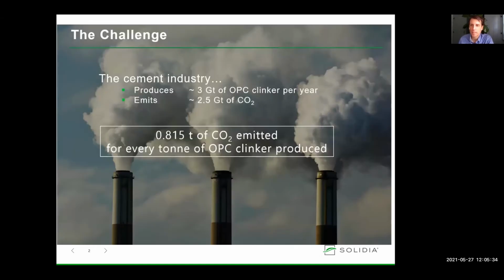I'd like to start off by stating a major challenge that we, the cement industry, are faced with. Annual global production of roughly 3 gigatons of clinker emits about 2.5 gigatons of CO2. On a per-ton basis, that's 0.815 tons of CO2 emitted for every ton of clinker produced. Solidia has precast and ready-mix technology solutions that can significantly reduce these emissions while simultaneously providing additional value to producers and customers.